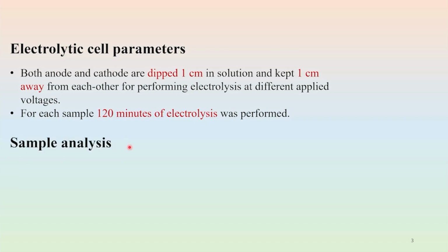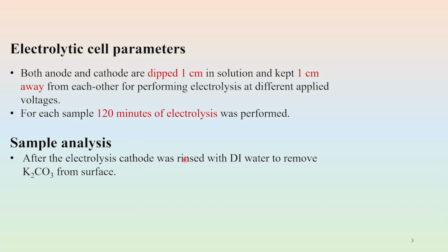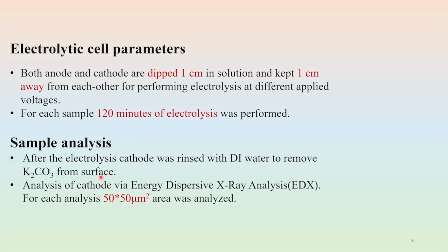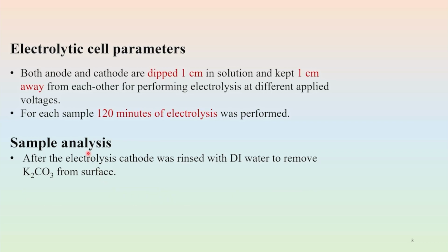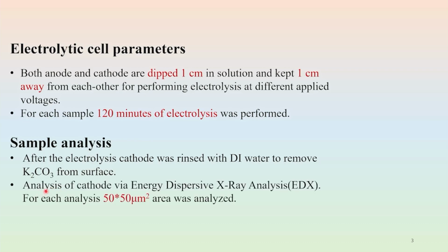Now let us move to the sample analysis. After the electrolysis, electrodes are pulled out of the solution and the cathode is rinsed with deionized water to remove potassium carbonate present on the cathode surface, as it would appear in further analysis. For the analysis of the cathode, the energy dispersive X-ray (EDX) technique is used.